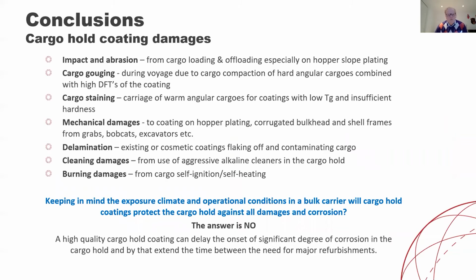So, as a conclusion, what kind of cargo hold coating damages do you typically have? You have what I already mentioned, the impact and abrasion damages from cargo loading and offloading. You have cargo gouging damages, which I also mentioned, from cargo compaction of hard angular cargoes, significantly higher also if you have high DFTs of the coating. You have the cargo staining when you are carrying warm angular cargoes with low Tg and insufficient hardness.